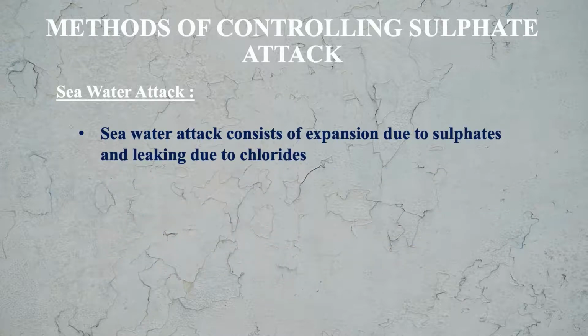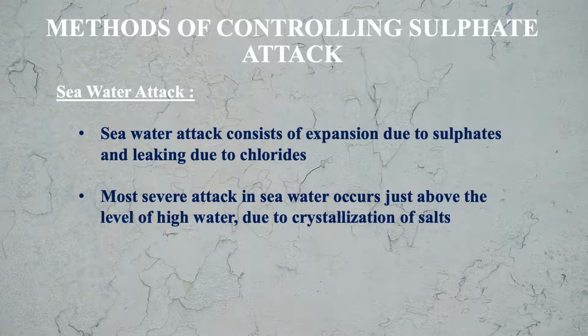Seawater attack consists of expansion due to sulfates and leaching due to chlorides. Because of the sulfates and the chlorides in seawater, they are affecting and causing expansion of the concrete. Most severe attack in seawater occurs just above the level of high water due to crystallization of salts. So we are seeing here at what level the concrete is being affected, and in what way.